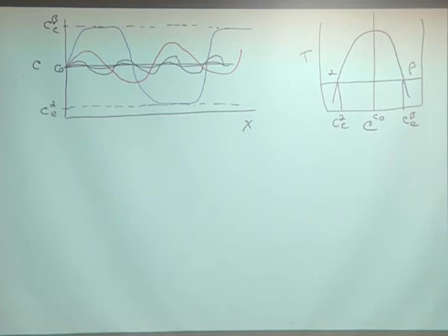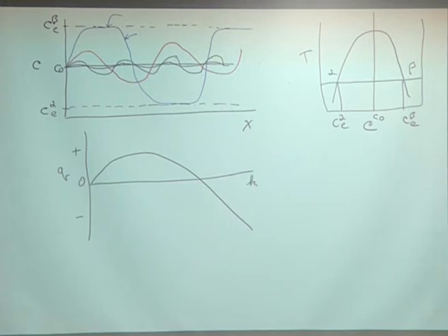Questions? Everyone see that? The reason why this composition profile goes to the equilibrium values has to do with the fact that this partial squared f with respect to c varies with composition. If you didn't have that, these compositions would diverge to infinity, right? Okay. I want to emphasize one other thing, and this is kind of a fun, hand-wavy illustration of the importance of these things. They're sometimes called dispersion curves.